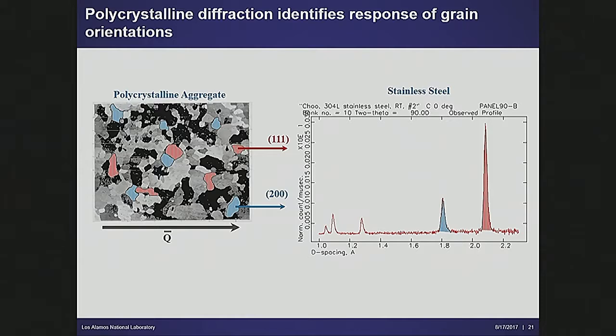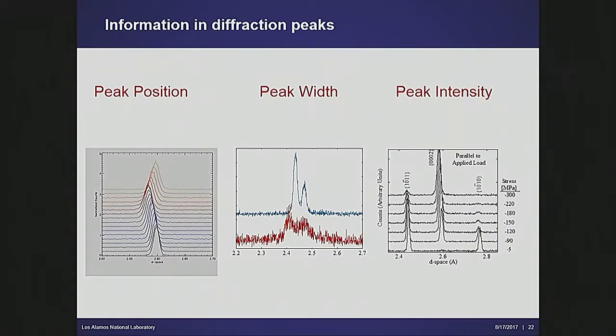So by now, you're familiar with polycrystalline diffraction. You're well aware that when you see these peaks, what you're doing is selecting out a set of grains in a particular orientation with respect to a particular load in order to make the measurements. In a cubic millimeter of material, if you've got a grain size of a micron or so, you've got 1 billion grains. And so you're looking at a subset of those. When you do diffraction measurements, you can pull out a peak position, you can pull out a peak width, you can pull out a peak intensity.